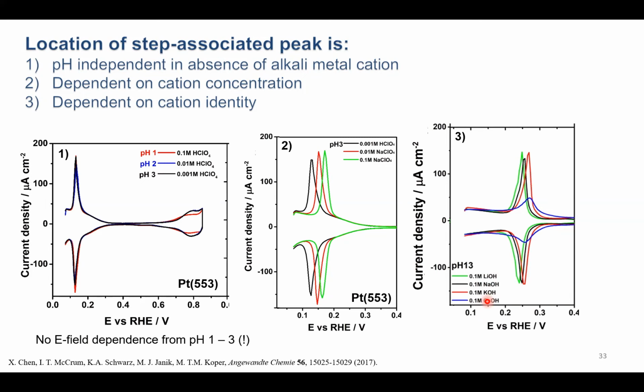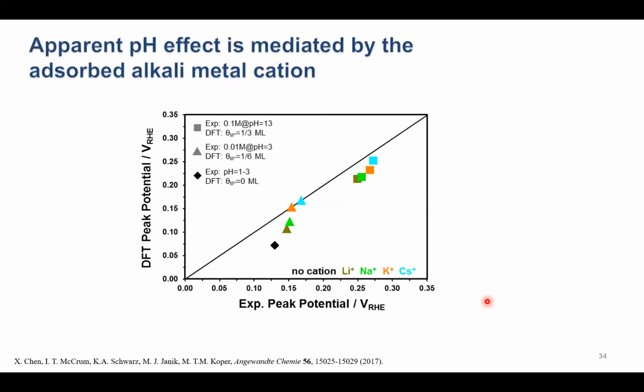And so this seems to support that this effect of pH is really an effect of the cation sitting close to the surface, which becomes increasingly favorable with increasing pH, and that weakens the adsorption of OH and water. And we can capture all of this with DFT. So now instead of just looking at no cation and a high coverage of cation, we can actually vary the coverage of the alkali metal cation and show that that allows us to capture the continuous shift of this peak with increasing pH. And so this black diamond here is the location of the peak in acid. We're showing the experimentally measured potential versus DFT predicted potential. And we see that it shifts positively with increasing pH. We find with DFT, this correlates with a higher coverage of cation along the step, and that shifts the peak more because it causes a greater weakening of OH and water adsorption.